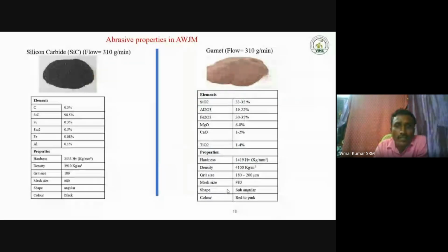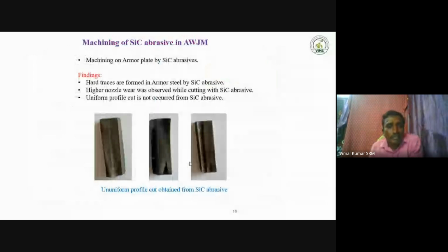So I already told that a variety of abrasives are used, but we use silicon carbide and garnet. These are the silicon carbide chemical composition and properties, and these are the garnet abrasive chemical composition and properties. As compared to silicon carbide, garnet has lower values. So we tried both abrasives in the water jet machine. Initially we tried silicon carbide. In this condition, silicon carbide has high hardness, so it easily cuts the armor steel. At the same time, it easily affects the surface. So it does not give a good surface finish, because of the high hardness.